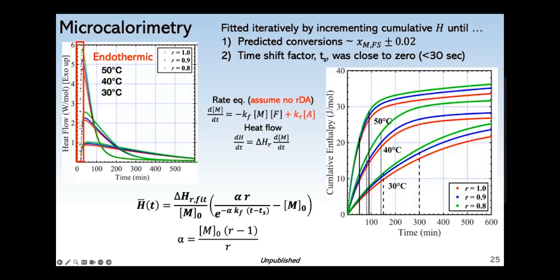So to do the corrections and fitting, I start off with the rate equation, assuming there's no reverse process. And then I solve it for the maleimide concentration. And so even though we expect some initial endothermic heat flow, in the long run, the heat flow will be dominated by the exothermic forward reactions. And after solving those, you get this fitting equation shown here at the bottom, and alpha is just a convenience variable. The fitting coefficients are the enthalpy of reaction, the forward rate constant, and this time shift factor. And when I integrate this for the first time, I start off at the exothermic peak here in the raw heat flow, but I clearly shouldn't have zero reaction enthalpy for the first hour.